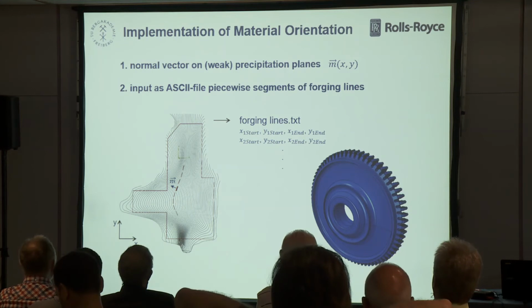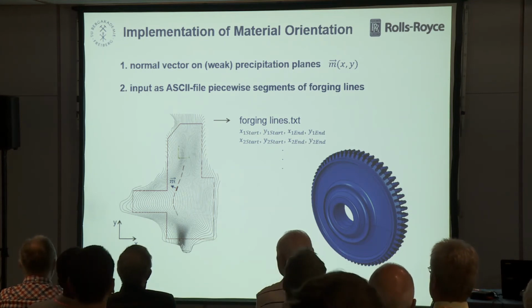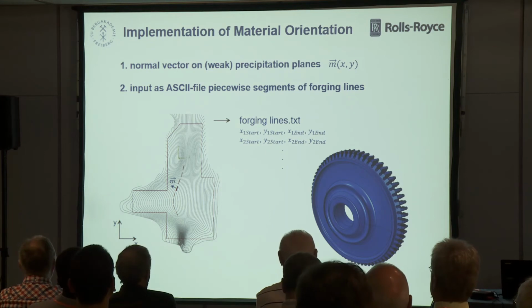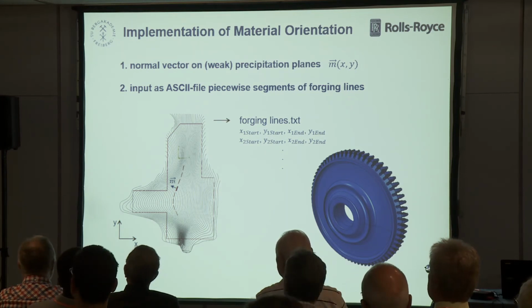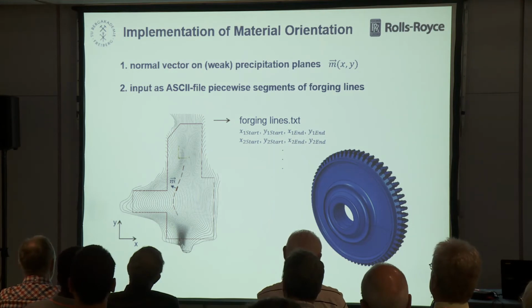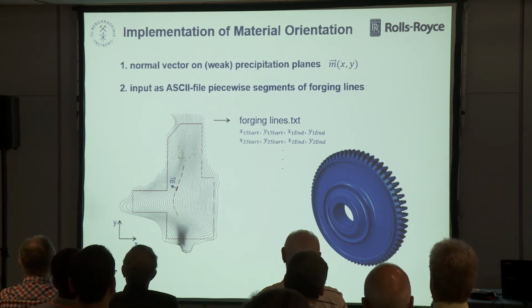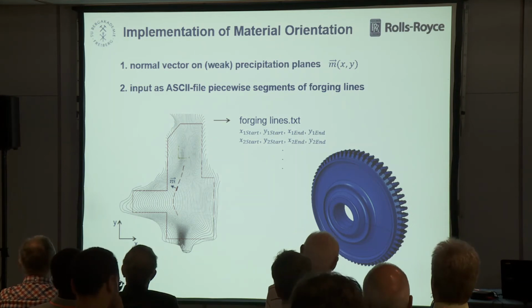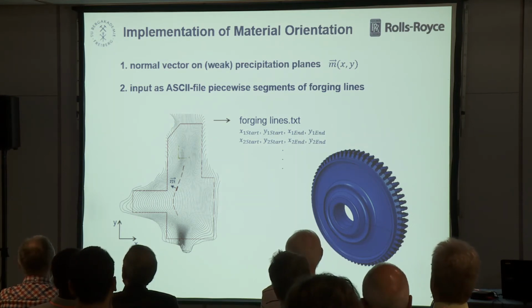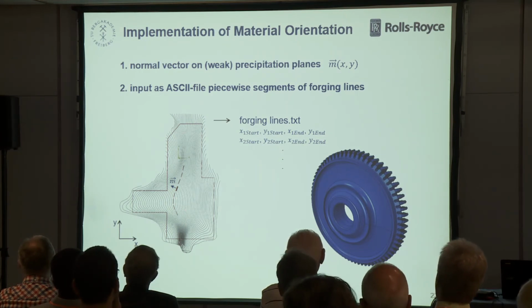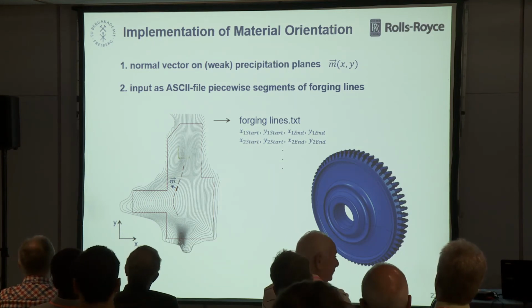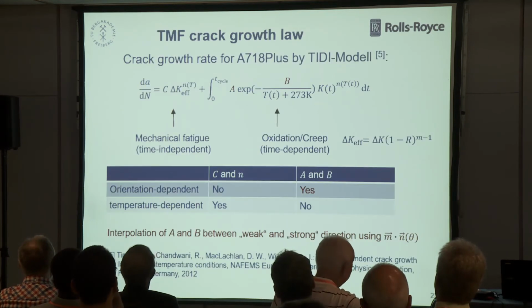Now we have another complication, because this orientation of the anisotropy is not unique in the whole structure. There's no homogeneous anisotropy, it is heterogeneous. So due to the forging lines, you see the forging lines, a piece is forged, and then from there the wheel or the disc is machined. So by an additional data file, we had to describe the shape of these lines and always the normal vectors. Okay, now we have the direction, and now we look for the propagation rate.